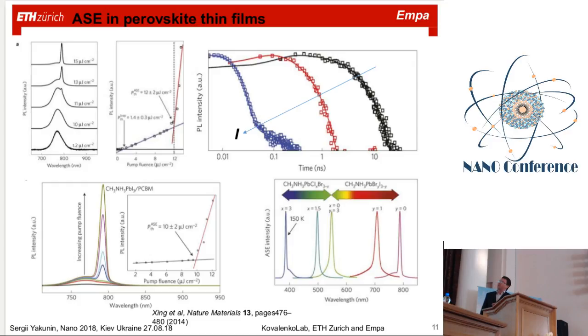So initially, at low pumping intensity, you just observe a photoluminescence curve, and just after a certain threshold in intensity, a very narrow and sharp line appears. And this line is already a partially coherent emission, showing the region where you have optical gain effects. And another way to prove this amplified spontaneous emission, where you observe photoluminescence lifetime, you see drastic acceleration of this lifetime after the threshold of optical gain.